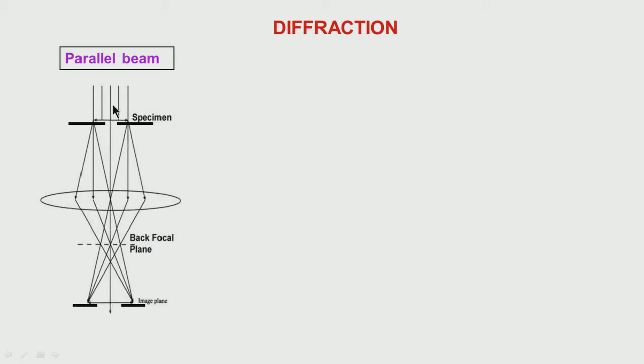Since it is an electron beam, I can focus the beam to a very small size, a parallel beam, and fall it on a specific area and get a diffraction. But when I try to do it, the intensity will get reduced considerably. Suppose I want a diffraction pattern from both the regions, then either you play with the beam, or the other way we can do it, in front of the specimen, keep a parallel beam and put an aperture.